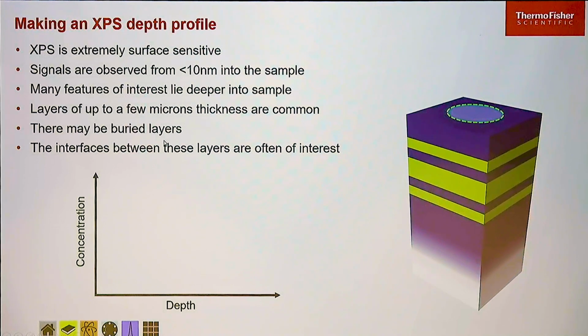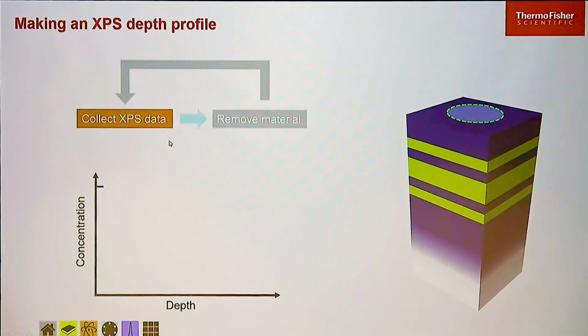And just to show this in a little bit more detail than James did, we're collecting our data from the surface, and as James said, that's 10 nanometers thereabouts, about 30 atomic layers. And we want to go deeper, so we want to understand in the layers below what's going on. So the process we follow is collect XPS data, then we etch the sample with the ion source. We'll raster over an area that's about 5 times larger than the area we want to collect our data from. The reason we do that is we want to be collecting data from the flat bottom of the crater. If we have the etch area too small, then we'll be risking collecting data from the edges of the crater, and that will mean we won't get as good depth resolution on the data, so we might start seeing layers that we've already removed, and it will blend in.